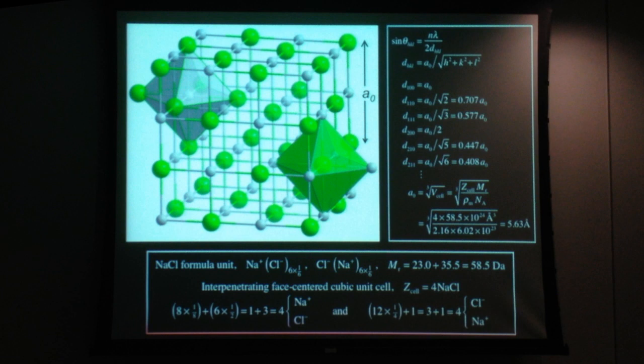Then with the wavelength in hand, they could measure the scattering from sodium chloride crystals at other wavelengths and calibrate the wavelengths of the X-rays obtainable from other sources. Remember that the X-rays are obtained by bombarding a target with a high-voltage beam of electrons, which causes intershell transitions to occur. When you promote an electron and then it relaxes, off comes a photon, and those photons are characteristic of the energy spacing between the shells. So looking at different targets and measuring the scattering from a given crystal, one can calibrate a whole spectrum of X-ray wavelengths.